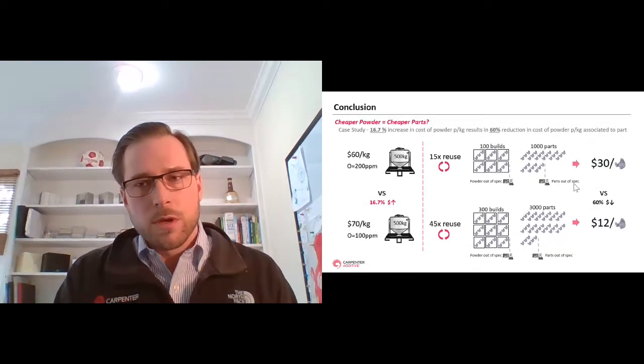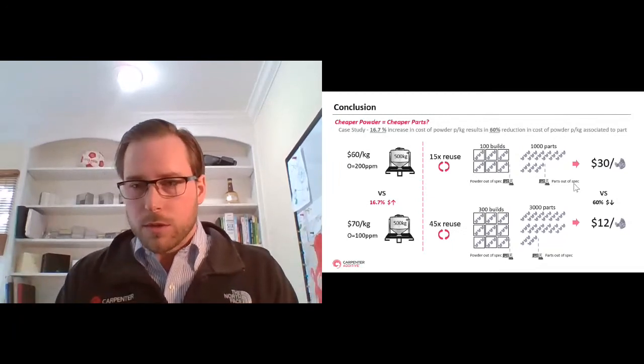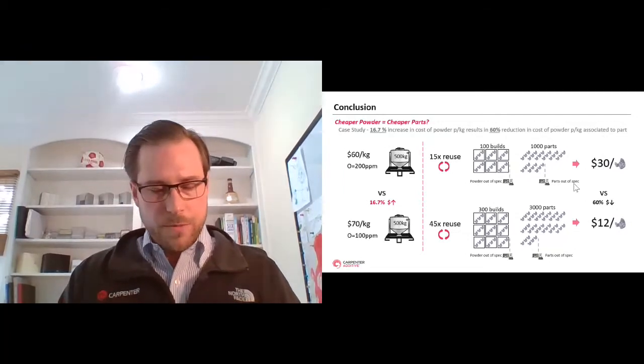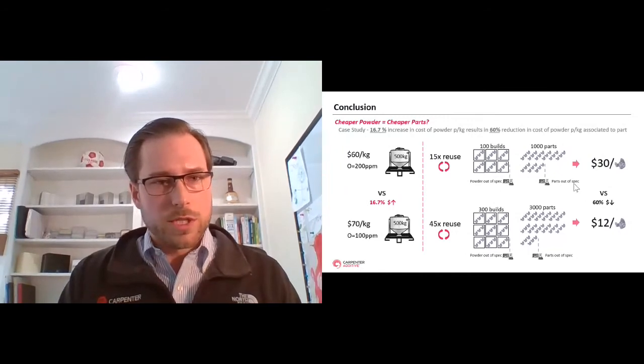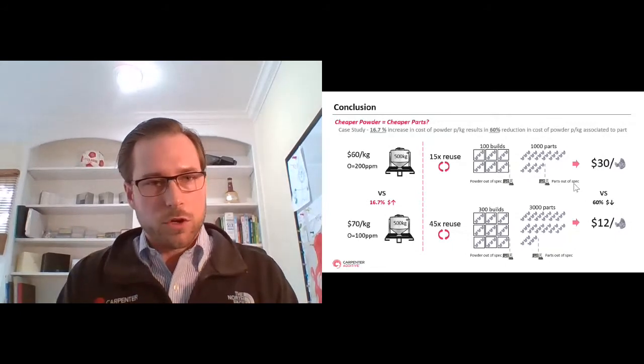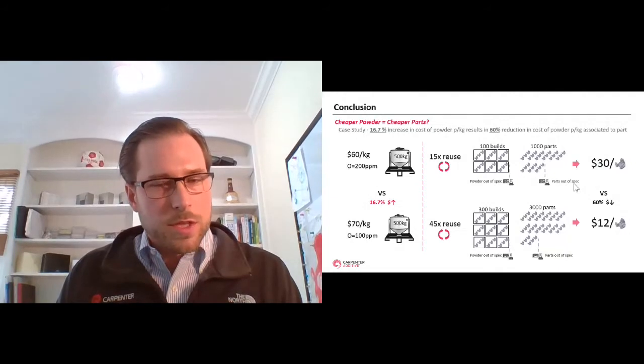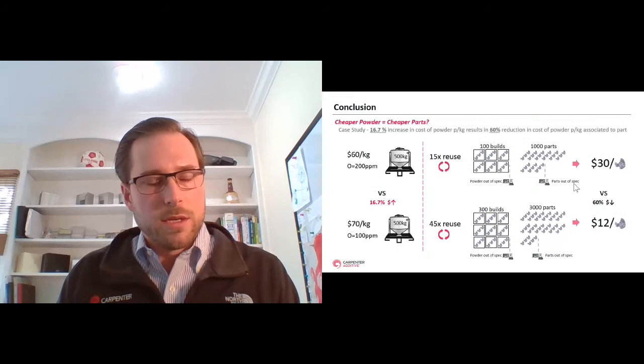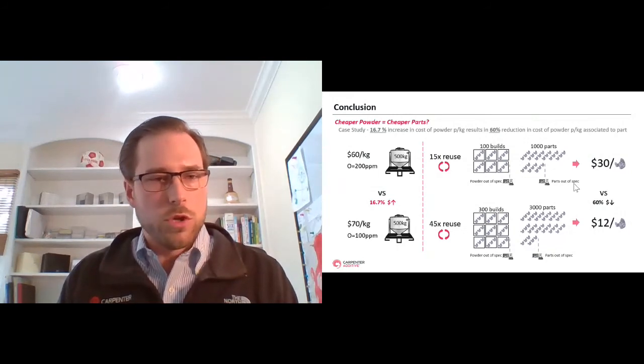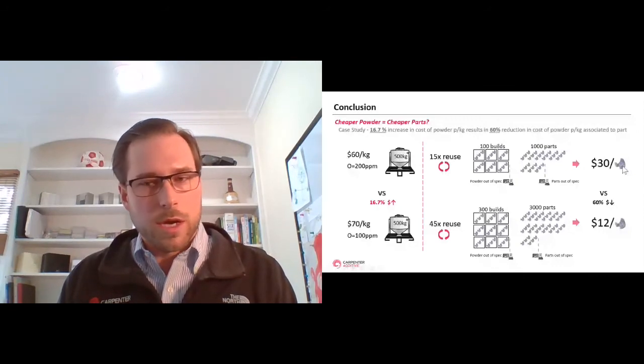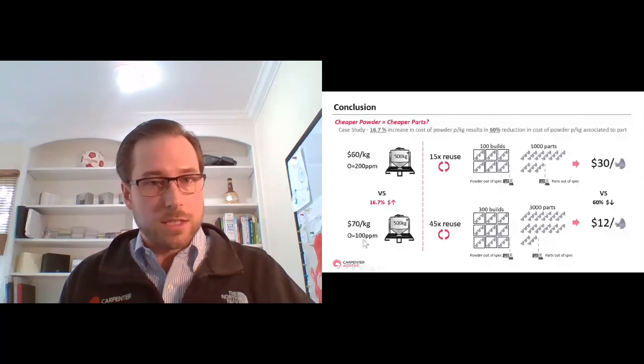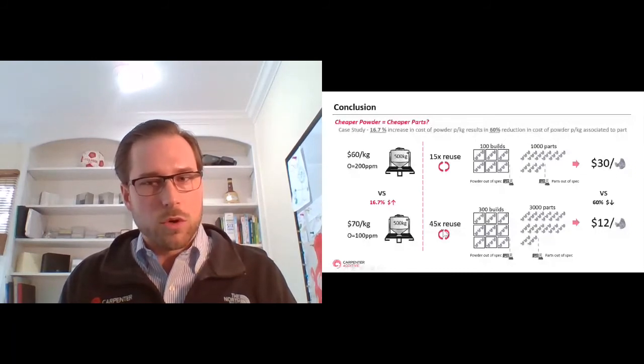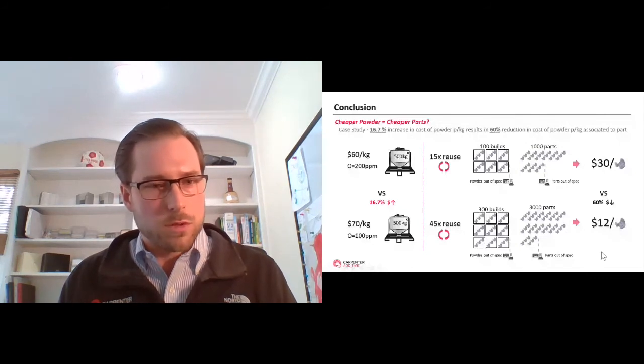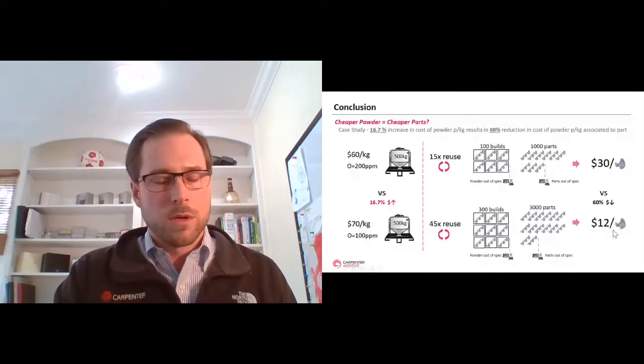And then from an economic standpoint, when you start to think about whether cheaper powder means cheaper parts, we're seeing the productivity of these machines increasing, and powder is becoming a bigger chunk of the cost of parts. In this scenario, and this is an illustration for a nickel alloy, if you paid $60 a kilo for 200 parts per million oxygen, let's say you could get 15 reuses out of it, that would equate to $30 per part. Whereas if you paid $70 a kilo for 100 parts per million oxygen, it would enable you, with this rate of oxygen pickup, to get 45 reuses, meaning your cost per part from the powder would be $12. So huge potential economic benefits of increasing powder reuse.